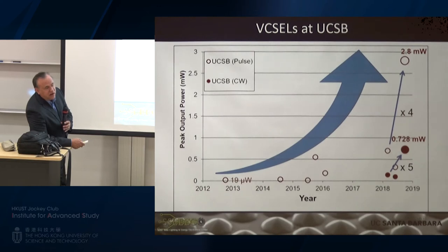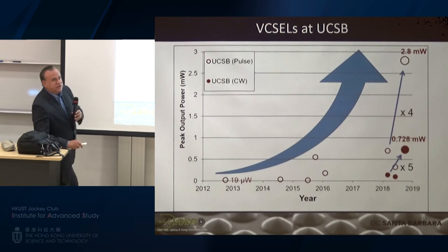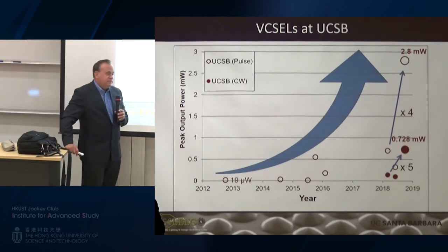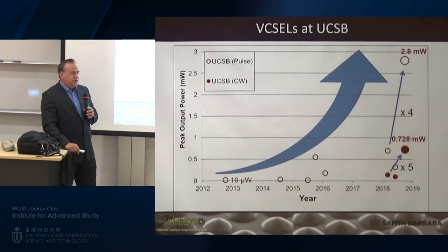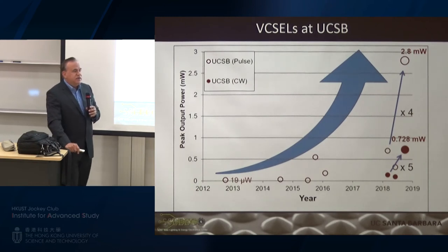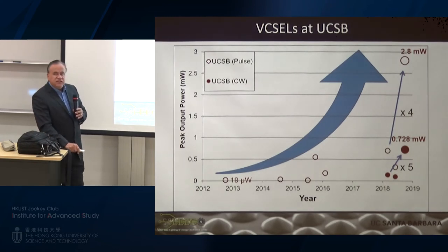Well, that's a short-range LiDAR for the face. But what is the uniformity? Because you've got to measure the reflection and all that. Right? Our yield's very high on these now, like 90%. It's better than our edge-emitting lasers. The 6x6 is very good. See, this is why VCSELs are so much cheaper than an edge emitter. The yields are higher. VCSELs are more like LEDs. You get 90% yields. Edge-emitting lasers, you're down at 40, 50% for a long time. And bigger areas.